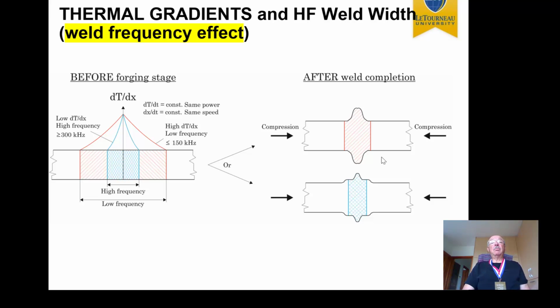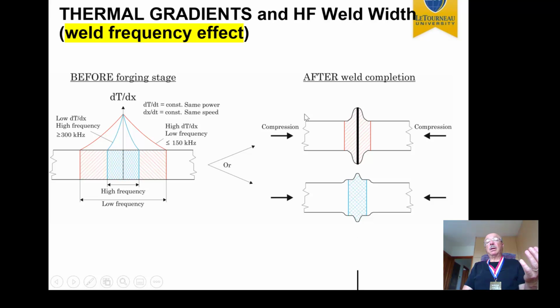The same happened when the frequency changed. In this case, it was not the cooling rate, but the thermal gradient, that is how steep the gradient was. Low frequency made it very wide, high frequency made it very narrow. So that basically said after welding it was a similar behavior, and we ended up again with bond lines which varied very little within this group of experiments.